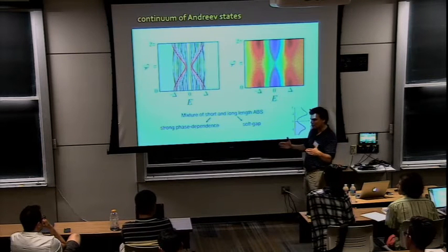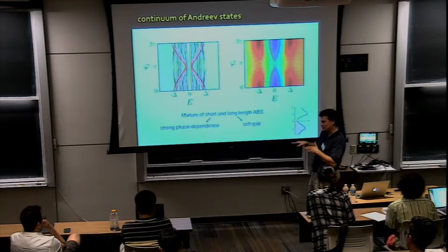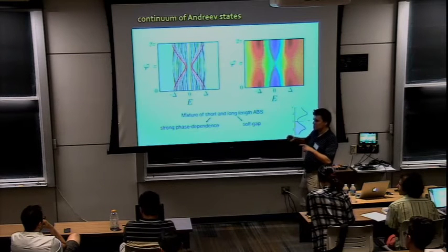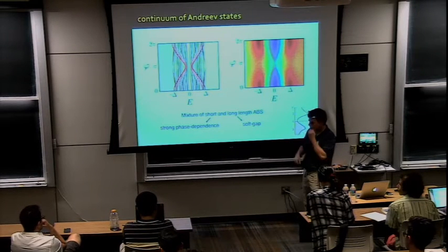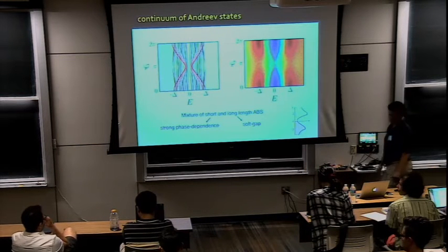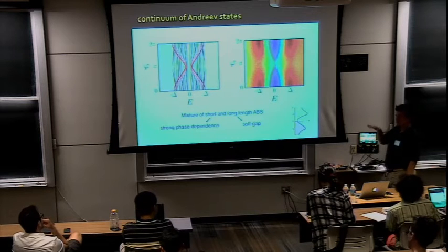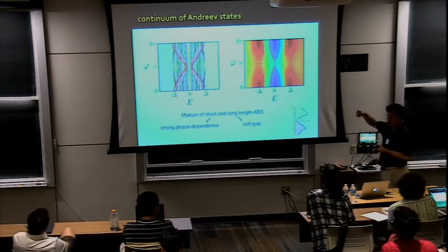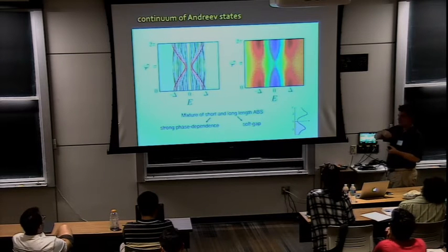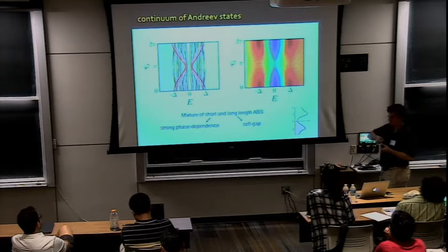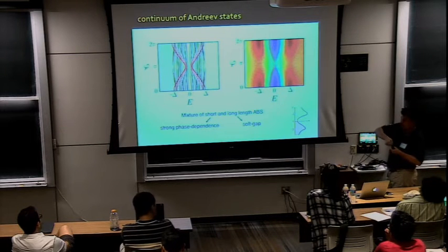But as you have a 2D system, you have higher and higher momentum states. Those correspond to angular trajectories, which have much longer geometrical paths. Those create many Andreev bound states. So really, it's the angle that you're coming in at. Yes, that is if it was ballistic. In addition, of course, you have disorder, which means your geometrical paths for the formation of some of your modes are effectively longer, because the disorder makes them take a longer route to go from one superconducting electrode to the next.